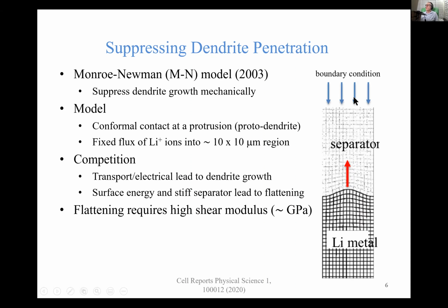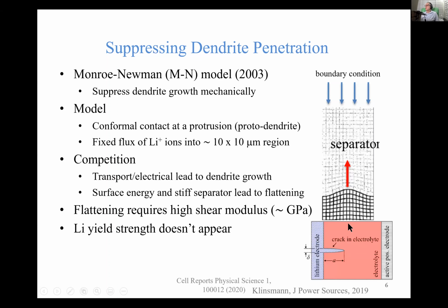And there's going to be a competition for whether the lithium deposits at the tip here, which will grow the dendrite, or whether it deposits out in the wings, in which case the surface is flattened. And one conclusion that they came to is that the flattening requires a high shear modulus, high for a polymer, of several gigapascals at least. It's interesting that their analysis doesn't mention yield strength of lithium at all. Now, this sort of architecture is pretty much universally used by everybody who thinks about or models dendrite penetration, in that you have lithium in perfect conformal contact with a solid electrolyte, just like here.